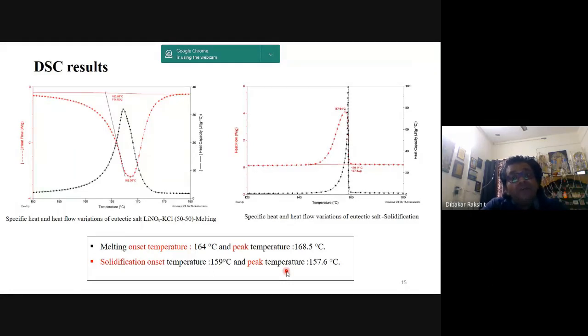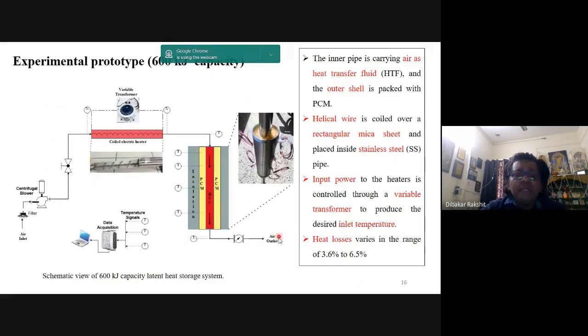By that you will know what inefficiencies you will be encountering when you are actually designing that thermal battery. So this was quite important, and it was not reported anywhere. When we were taking those salts, we did not understand how they would behave when we made the binary eutectic and attempted to utilize it for our requirement of 140 degrees centigrade to 180 degrees centigrade, that energy storage criteria of temperature. On that basis, we found these results to be quite interesting. Anyways, now we proceeded further.